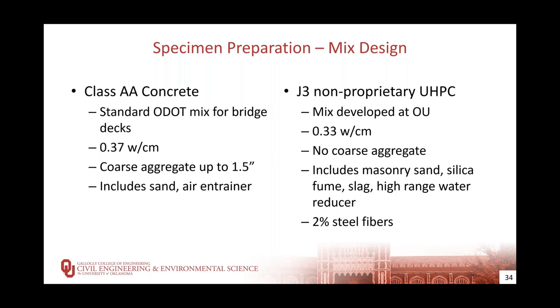The J3 mix, again, was developed at OU. It uses a much lower water cement ratio and includes masonry sand, silica fume, slag, and high range water reducer. The J3 mix included 2% steel fibers, which is very typical for UHPC mixes.